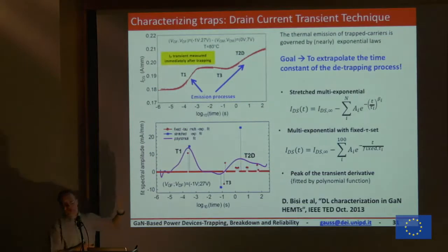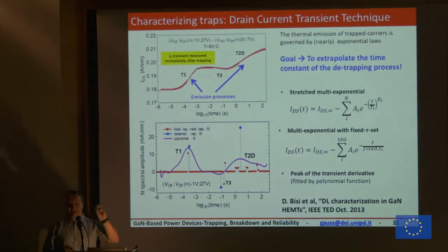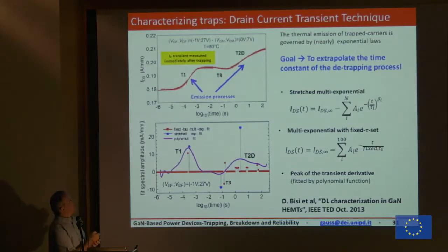So with this plot, we just try to understand important information. We have 3 kinds of traps that are affecting my transient evolution. So my current collapse is not caused by a single trap level, but by 3. And they have a time constant that can be from 10 to the minus 4 to 10 to the 2. Okay, how can we characterize these traps?